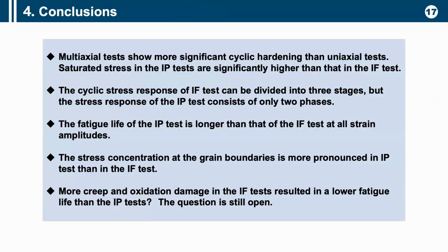So we can get some conclusions. Multiaxial tests show more significant cyclic hardening than uniaxial tests. Saturated stress in the IP test is significantly higher than in the IF test. The cyclic stress response of the IF test can be divided into 3 stages, but the stress response of the IP test consists of only 2 phases. I didn't explain this phenomenon.